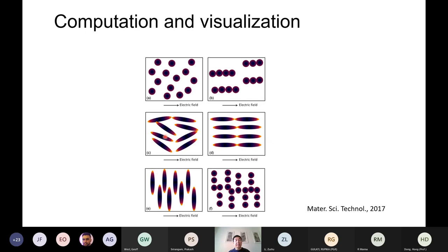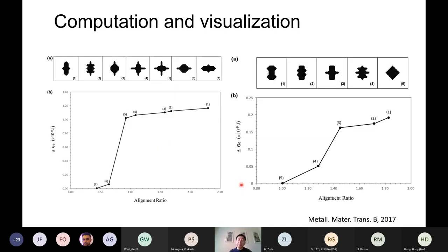However, if those inclusions are in this ellipsoid shape, but perpendicular to the electric current, they will be fractured to form very small parts. So those are according to calculation. And then a student did another case. If we have an inclusion and that inclusion tries to grow, in that case, what kind of morphology will this electric current affect?